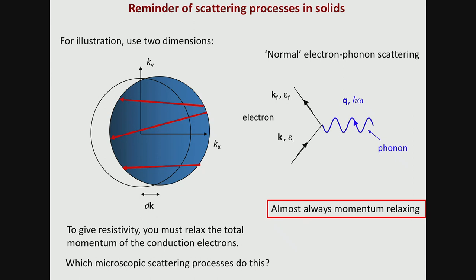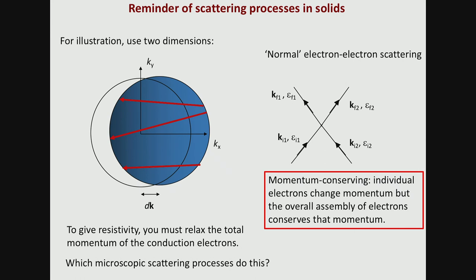So one process you have is what's called a normal electron phonon scattering process, where some electron on the Fermi surface will either absorb or emit a phonon. The energetics means that that's a quasi-elastic process, and so you could certainly create resistivity with these normal electron phonon processes, and in almost every case, that's what you're doing. Almost always, normal electron phonon processes are momentum relaxing, and anything in bulk which is momentum relaxing is the enemy of hydrodynamics. We'll come to the exception later.